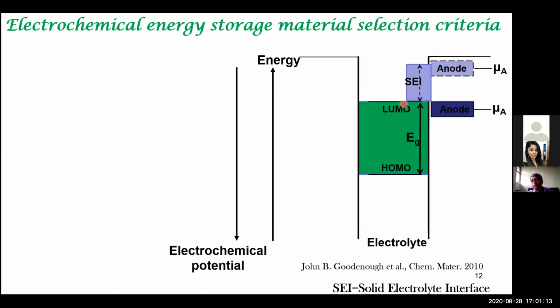This is a very big open problem. What is the composition of the SEI? How does it work, and so on? It allows lithium to transport, but it doesn't allow electrons to transport. A similar process can occur in the cathode, so a cathode SEI is formed. Once the cathode SEI is formed, there's an insulating layer, therefore there's no more electron transfer. So finally, the cathode and the anode will be at these levels, and there's no more electron transfer between the electrodes and the electrolytes. The electron transfer will be only from the electrode to the lithium salt.